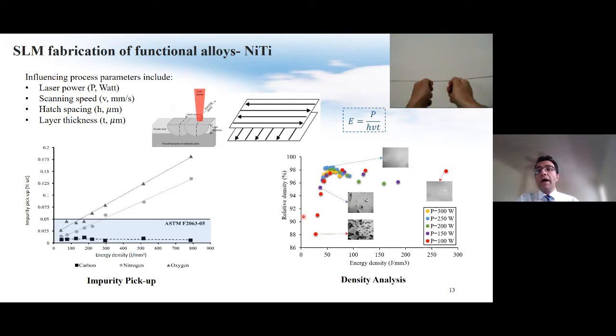We observe, as you can see here in this graph, higher density with higher energy input, which was desirable, but also higher impurity pickup, which was undesirable. Per the ASTM standard, we selected a range for the process parameters that met the requirement of high density, allowable impurity pickup based on the standard for the biomedical application, and good surface quality, all desirable for biomedical application.